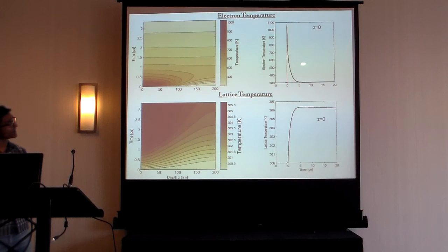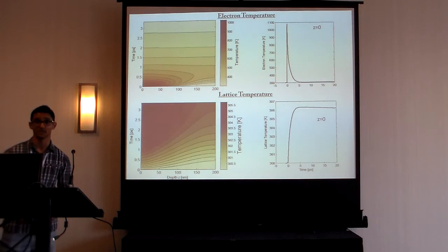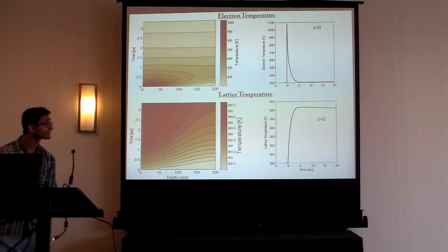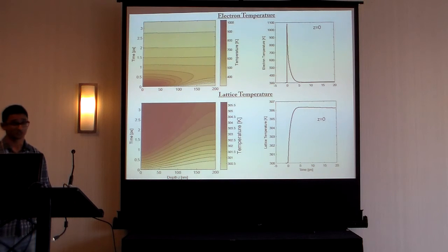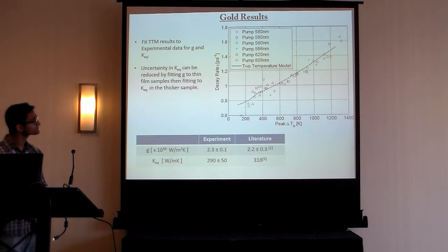Looking at the top right graph, which shows the surface temperature profile of the electrons, you can see that the transient signal looks much like the differential reflectivity signal. And again, this is because the differential reflectivity and the change in electron temperature are linearly related. So once again, we apply exponential fits to these transient temperature signals and extract the decay rate, much like we did with the experiment data. And we plot them together on a graph.